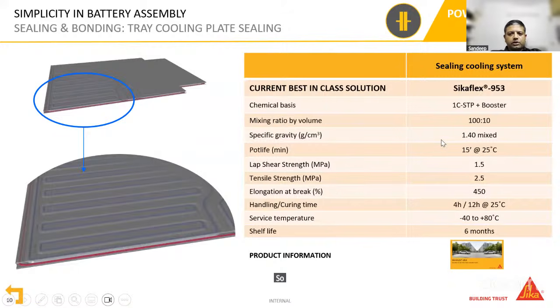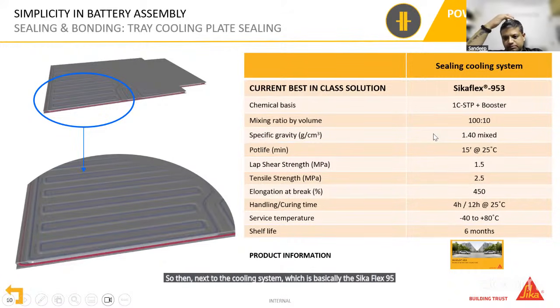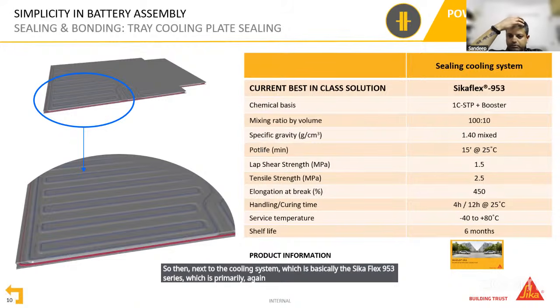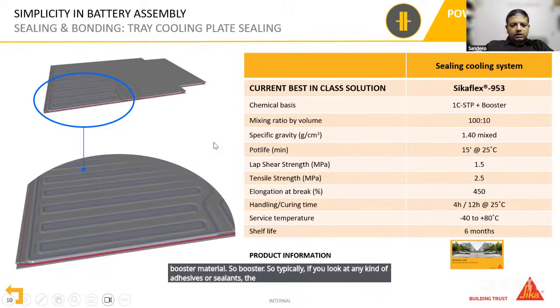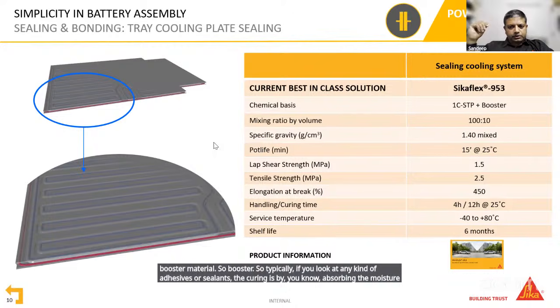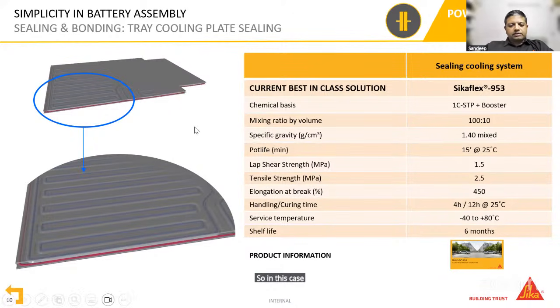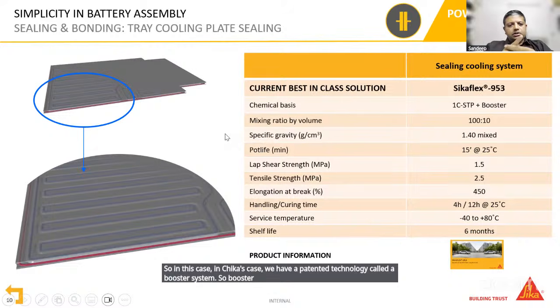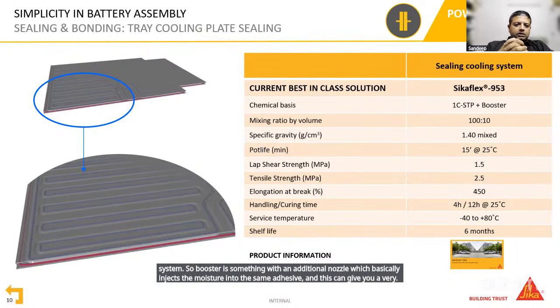Then next is the cooling system, which is basically the Sika Flex 953 series, which is primarily again an STP, silane terminated polymer plus a booster material. So typically if you look at any kind of adhesives or sealants, the curing is by absorbing the moisture from the atmosphere. So in Sika's case, we have a patented technology called a booster system. Booster is something with an additional nozzle, which basically injects the moisture into the same adhesive, and this can give you a very low curing time.